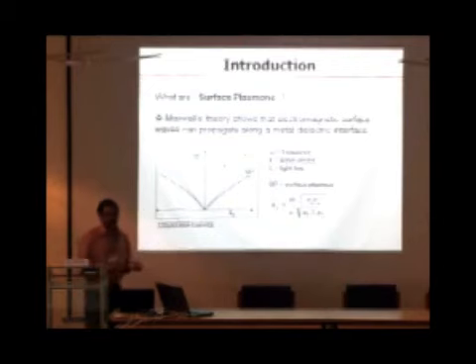If we solve Maxwell's equations, the wave equation, you can get the solutions that for TM polarized light, where your electric field is along the surface, parallel to the surface, you can excite the surface modes. Now if you have a metal and dielectric interface, you have lots of free electrons, which oscillate in tandem. So you have a charge density wave traveling as a surface mode at the interface of your metal and dielectric. That's the surface plasmon polariton wave.